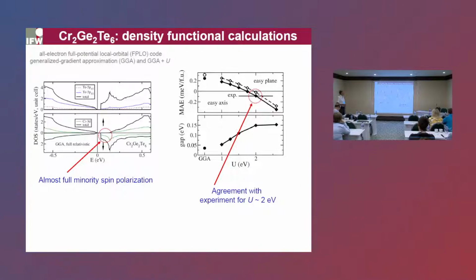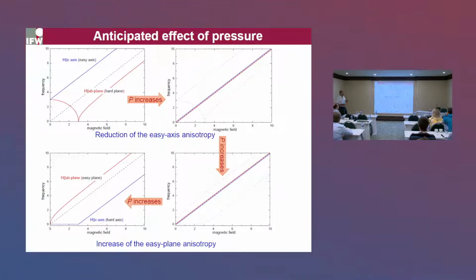The next finding was that it was really necessary to add the correlation energy between the electrons, because in its absence, the calculated magnetic anisotropy was of the easy plane type, which contradicted the experiment. However, increasing U up to, say, 2 electron volts, quite a good number, one could find a very good match between experimental findings and the theory, suggesting that we have a reasonable description of a single layer system in terms of the single ion anisotropy and polarization of the electron bands. So now the final question which was interesting to us: how can we change this magnetic anisotropy? Because it would be important to have some handle which could enable us to tune these very important magnetic properties.